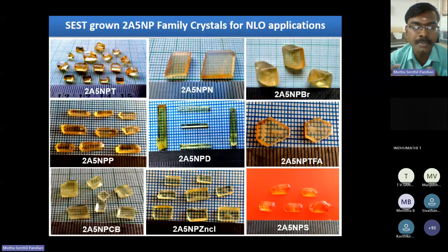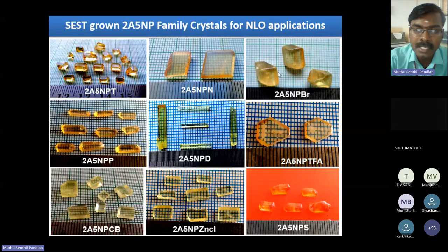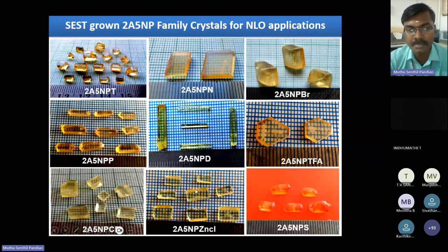size. Also, due to the daily temperature fluctuation, you see the entrapment of solvent molecules into the crystalline matrix is responsible for this kind of milky opaque regions, low angle grain boundaries, and micro cracks in the conventional method grown crystal, which we cannot avoid in the conventional method.